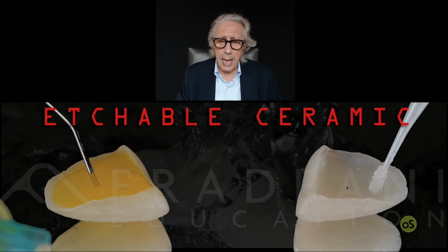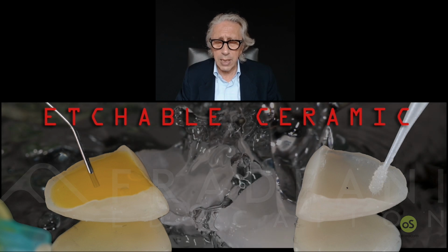So I remind you that we discussed before about the etchability of the ceramic. I told you that we have to use on lithium disilicate 20 seconds only, on the 4.5 or 5% of hydrofluoric acid. That is what you have to do, 20 seconds. Then you put silane, of course, and then you bond it.